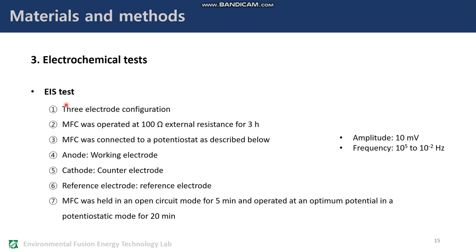Electrochemical impedance spectroscopy. EIS test for anode electrodes was carried out in a 3-electrode configuration. After the medium change, MFC was operated at 100 ohms external resistance for 3 hours. Then, the MFC was connected to a potentiostat as described below. The anode as the working electrode, and the cathode as the counter electrode, and a Ag/AgCl electrode as the reference electrode in potentiostat, when measured the anode.